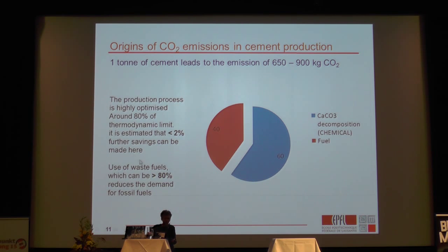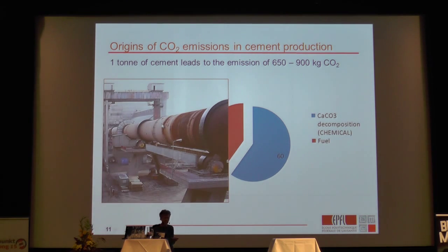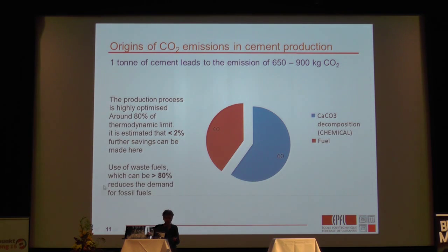And furthermore, this cement plant is a very flexible tool which doesn't have to use fossil fuels, can use waste plastics, waste oils, many other things that would be quite hard to dispose of safely in any other way. So not only can these wastes be disposed of safely, but their calorific value can be put to good use. And typically in Europe, plants can operate at more than 80% of waste materials.